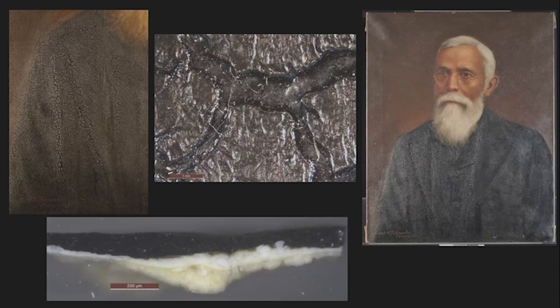And what I was talking about with the experts in Mumbai was that often these black jackets were painted in a single sitting. So what you have is that thick initial layer of paint, and then you have a much more glossy, high-medium-containing one to just map out the details like the buttons and the lapels. And I think what that is in terms of the cracking is just something that's been added far too soon, and that's why you have it rather than any additives in the paint. So it's more artist technique rather than material, and apparently it's very common amongst paintings of this phenomenon.